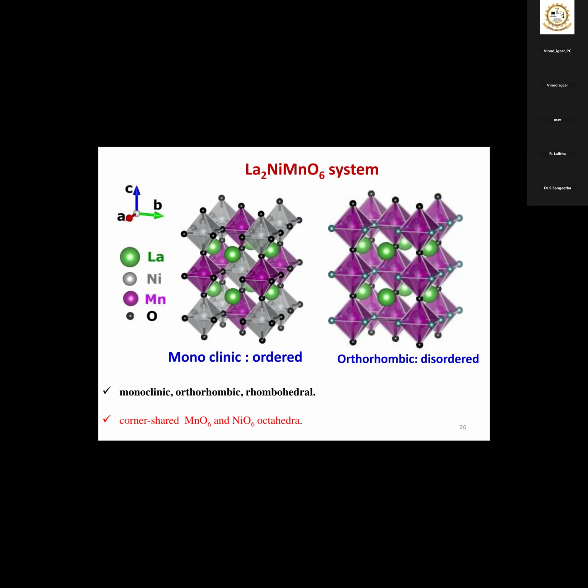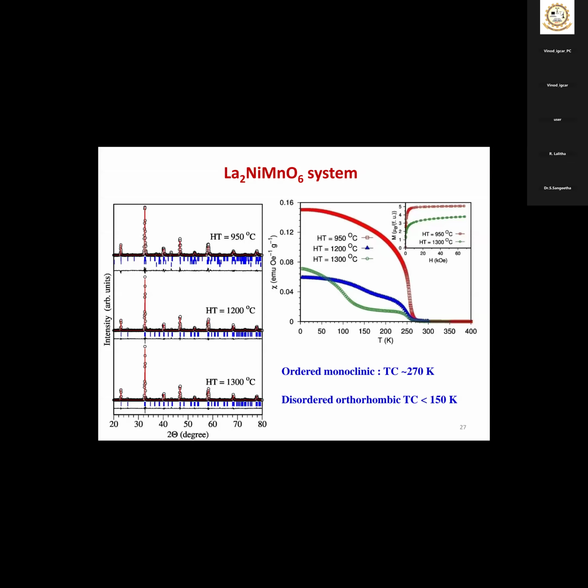The second one, right side figure, you can have a manganese-oxygen-nickel bond, manganese-oxygen-manganese bond, nickel-oxygen-nickel bond. So it is complicated. You see how you can control it. One way is synthesis temperature. What we observed is if you do the synthesis at a very high temperature, chances of disorder is more.